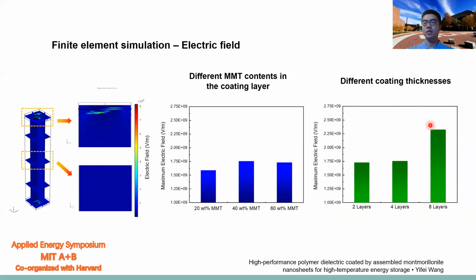One possible reason is that when the coating layers become thicker, the MMT nanosheets are tilted a little bit, and these tilted MMT nanosheets touch each other much more easily, which can finally result in an enhancement of the electric field in some localized regions. Previously we mentioned that this sample has the highest value of the ratio of GXY to GZ, but now it has a very high electric field inside the coating layer, and this becomes a drawback of the thicker coating.